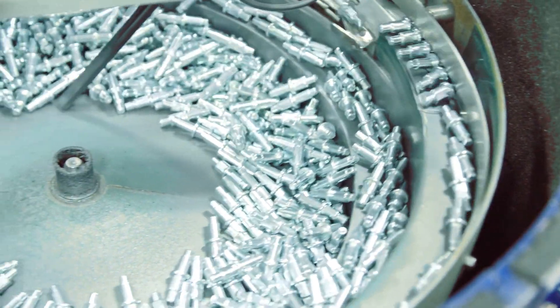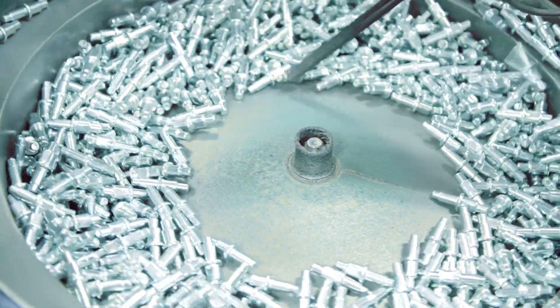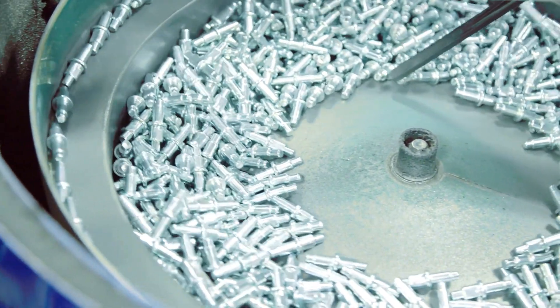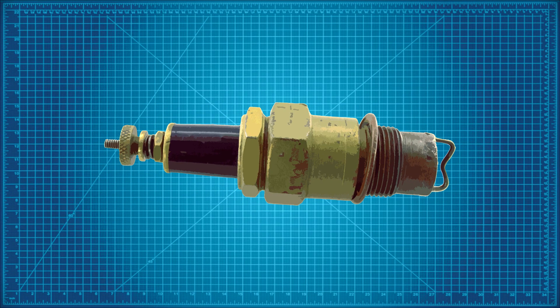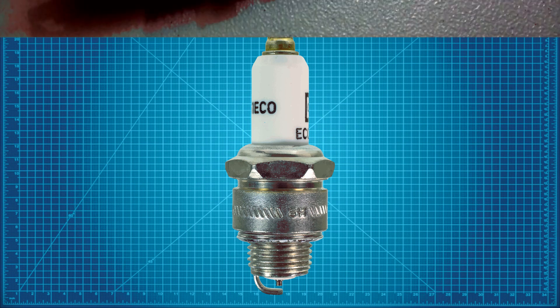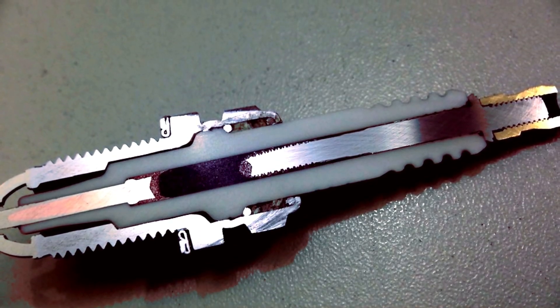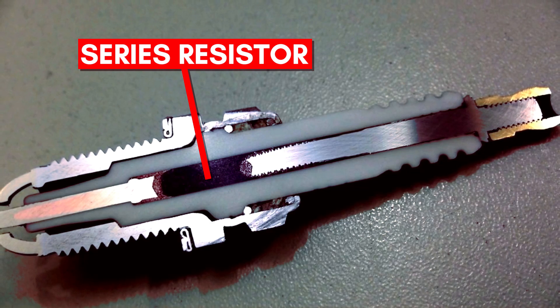Because of the intrinsic differences in construction, sintered alumina plugs use superior glass and metal powders for sealing in combustion gases. This improved upon the less reliable brazed sealing used on older plugs and made them more tolerant of high cylinder temperature and pressures. Some of these plugs began to incorporate a ceramic series resistor in order to reduce RF noise created by spark generation. The importance of this new feature was further underscored as electronics started to migrate into vehicles.